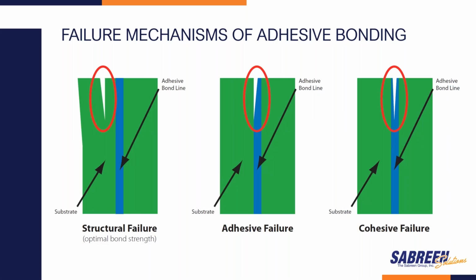So let's examine and briefly define what kind of failure mechanisms we generally see in industry. And it's very important to understand where the failure mechanism occurs, and that's the first step towards solving a problem. So in the center photo, you can see adhesive failure. That's the most common mechanism that we see. And adhesion failure is when the adhesive bond line separates from the two polymers that it's joining. And these polymers can be like or dissimilar materials.